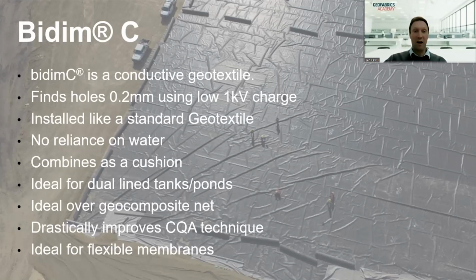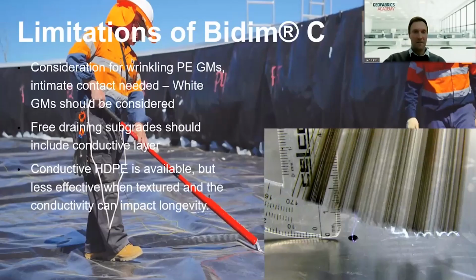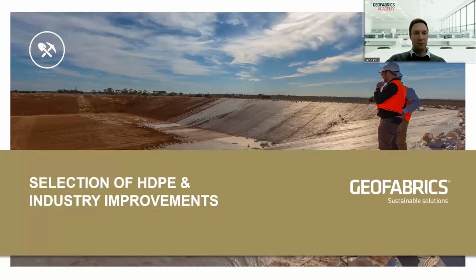So it's a really simple, dry and accurate means to test liners and panels between seams, and it's drastically improving your CQA methods. Until recently, I think the idea was that it was better for flexible membranes because you do want that intimate contact with the primary liner and the conductive layer. But essentially, if you've got a wrinkle there, you can just compress it with your foot, and we've found that it's quite effective. And there's ways to limit your wrinkles through certain methods, and I'll touch on that as well. I'll move on from that.